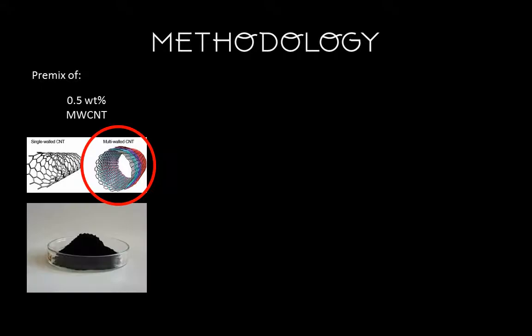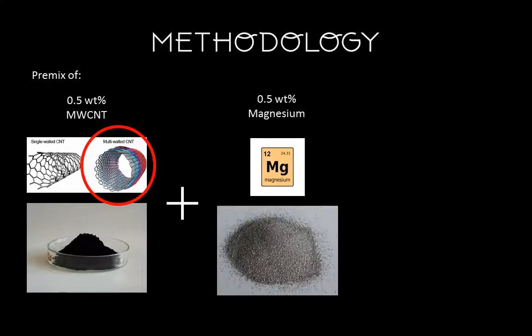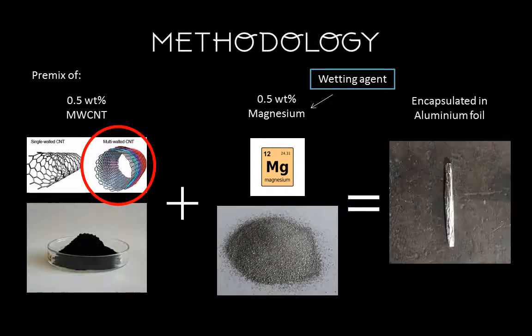Now, we will move on to the methodology. First step is to premix 0.5 weight percentage of multi-wall carbon nanotubes with 0.5 weight percentage of magnesium. The purpose of magnesium is as a wetting agent to bridge the carbon nanotubes to the metal matrix, and both of the materials will be encapsulated in aluminium foil.